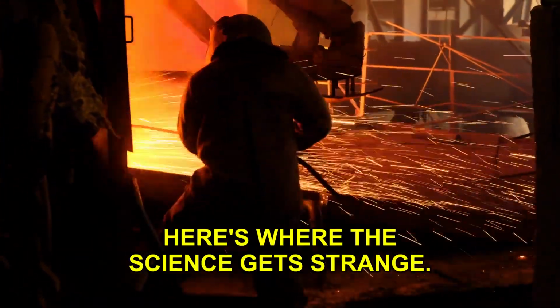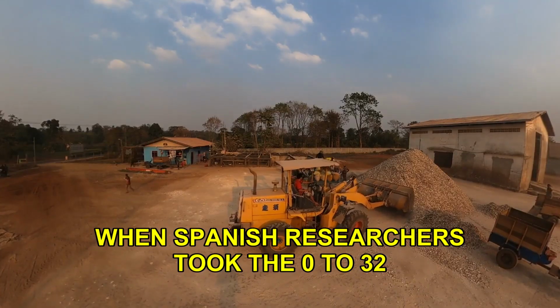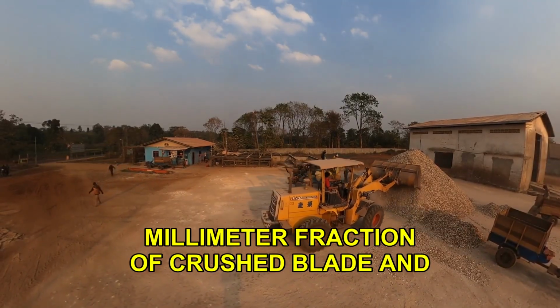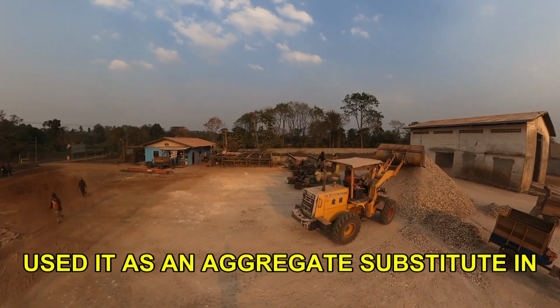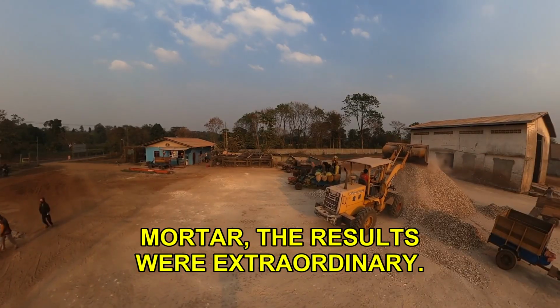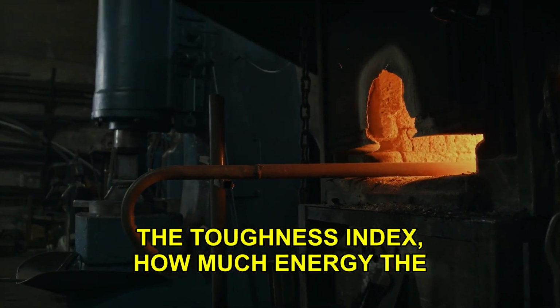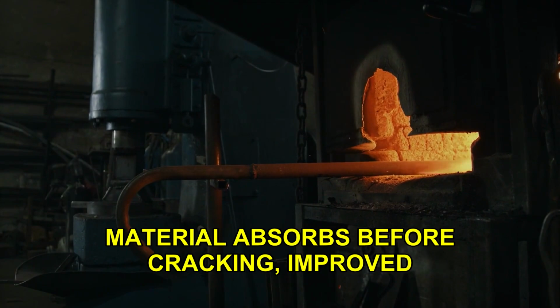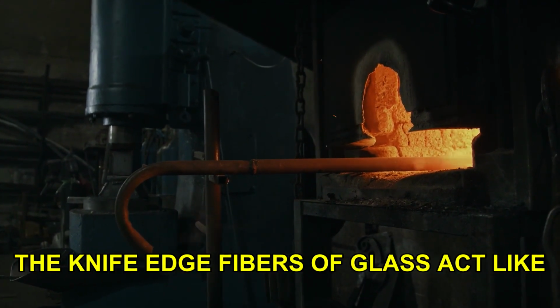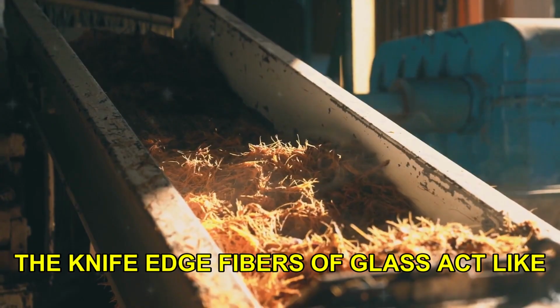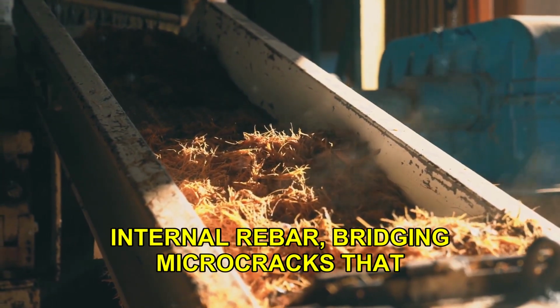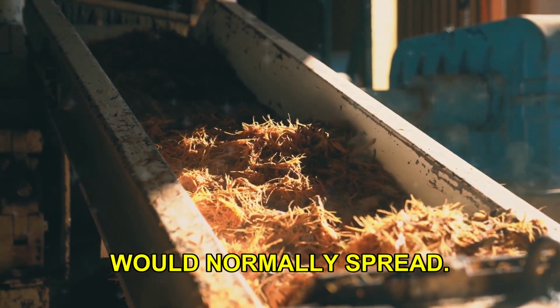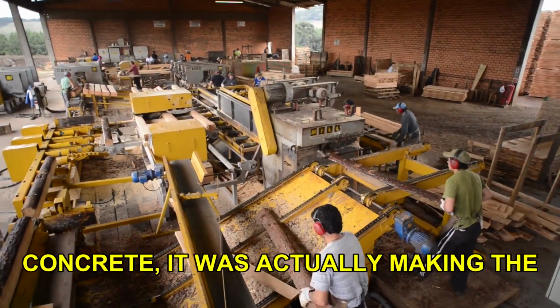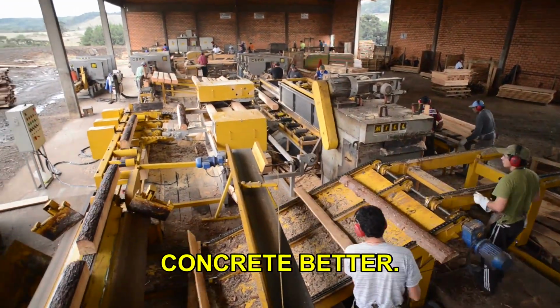Here's where the science gets strange. When Spanish researchers took the 0 to 32 millimeter fraction of crushed blade and used it as an aggregate substitute in mortar, the results were extraordinary. Porosity dropped by over 23%. Flexural strength jumped by 36.5%. The toughness index, how much energy the material absorbs before cracking, improved by nearly 250%. The knife-edge fibers of glass act like internal rebar, bridging microcracks that would normally spread. The blade was not just disappearing into concrete, it was actually making the concrete better.